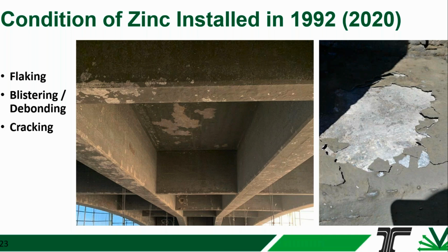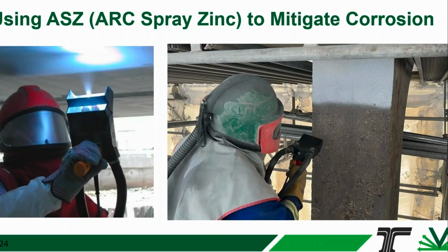So what are we talking about here when we talk about arc sprayed zinc or metallized zinc? We are basically taking pure zinc in wire form. We're melting those wires together in an electric arc, and we're blowing that molten zinc onto the prepared concrete surface using compressed air. And that is basically the process that's used for putting the zinc onto the concrete surface.